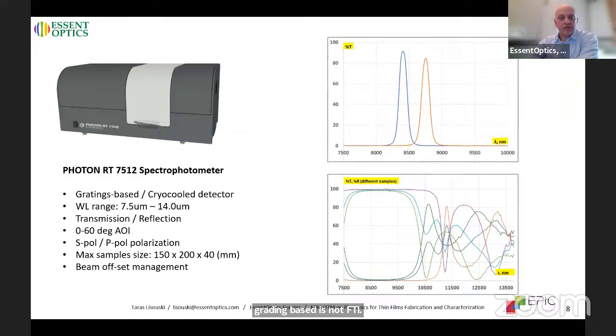We moved to long wave infrared last year. This system is grating based, not FTIR. We cover the range from 7.5 to 14 microns, and it is designed for transmission and reflection measurements at different angles of incidence and polarization of coatings and samples with coatings optimized for the long wave infrared range. We can even measure very thick samples at different angles and also compensate for beam offset while measuring transmission.